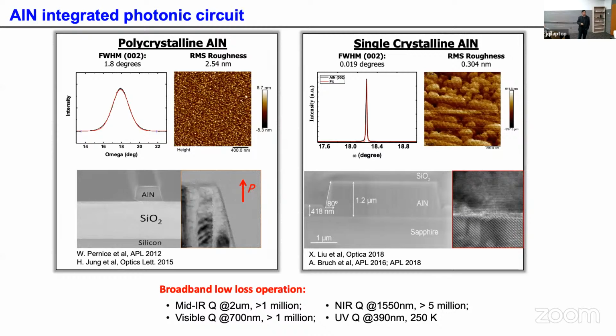The two types of material we've been using: one is polycrystalline aluminum nitride, which is sputtered on the dielectric layer to create a waveguide. Those are polycrystalline, but the domains are very small, less than 20 nanometers. And that's why you can have a high Q. If you do an X-ray rocking curve, you see about a 2-degree rocking curve. The roughness on the surface of the as-grown material is about 3 nanometers, and you can polish it down to about 0.1 nanometer roughness.